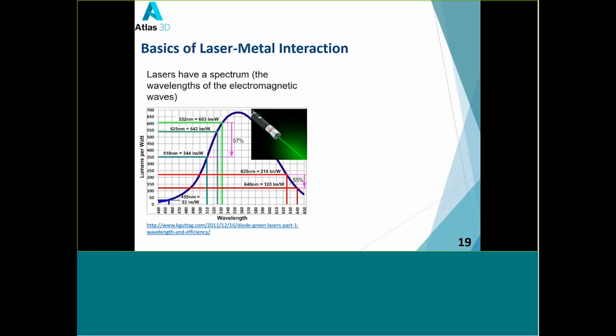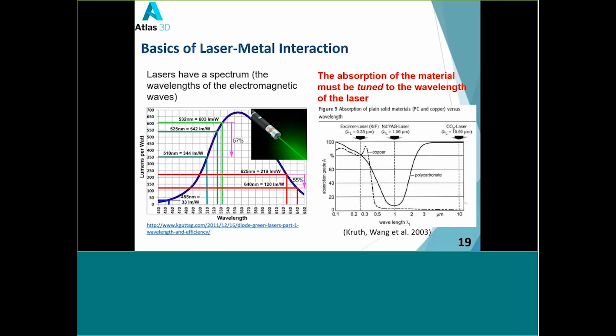So in order to model the whole AM process, the first thing you need to think about is how to model the laser metal interaction. We know that lasers have a spectrum. So when we model the laser metal interaction, we need to model how the material absorbs the laser. We can see that for different wavelengths of the laser, the absorption of a single material is different. For example, here, if you want to melt the copper with a laser beam, you don't want to use the CO2 laser because with the CO2 laser, the absorption rate for copper is pretty low. Most of the energy just reflected.